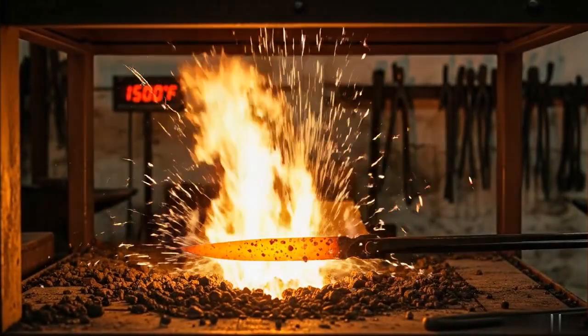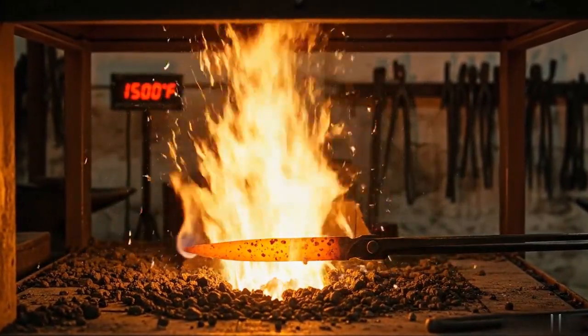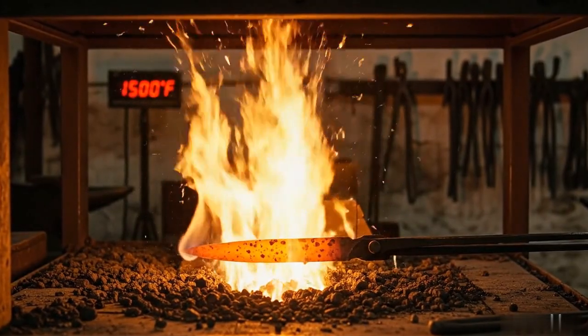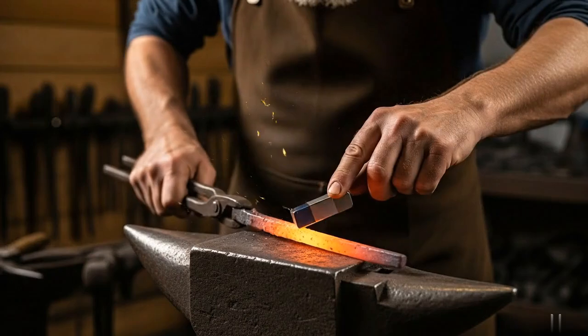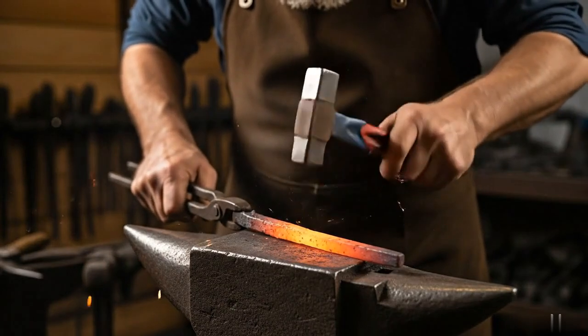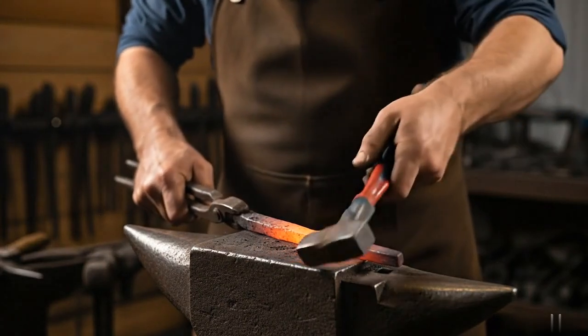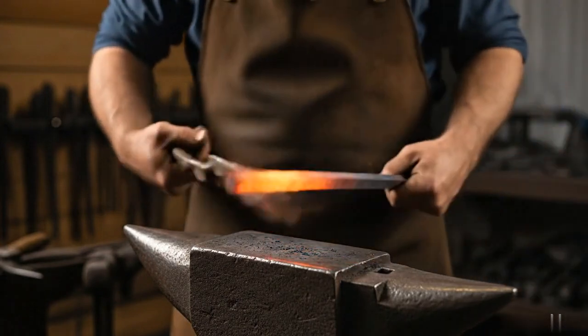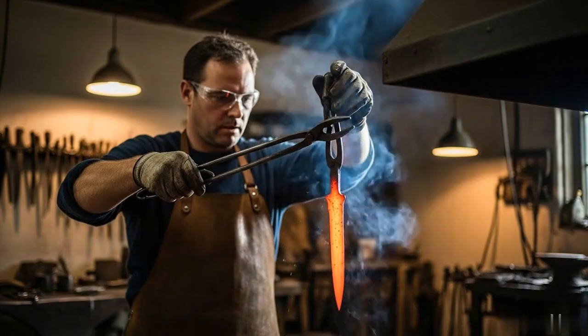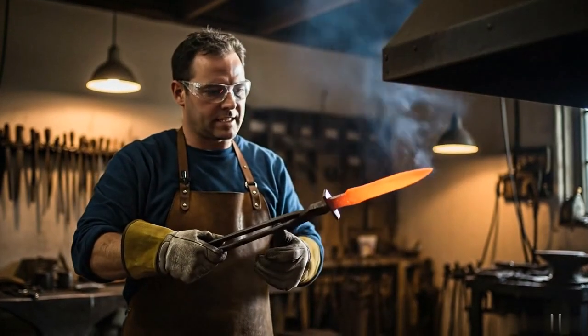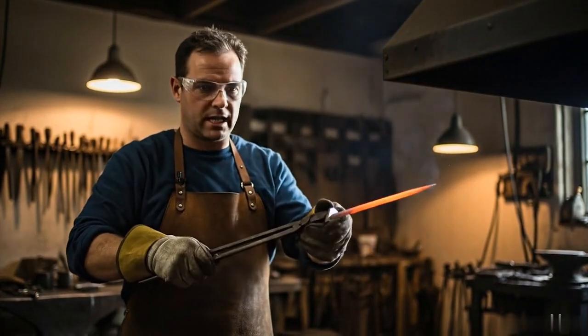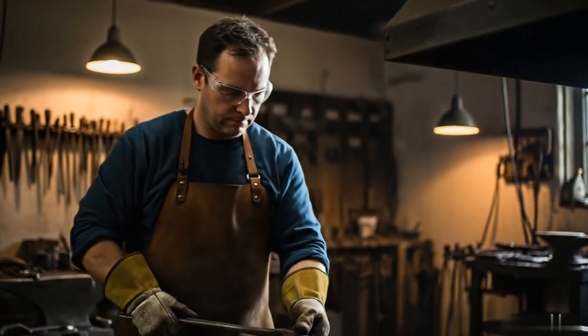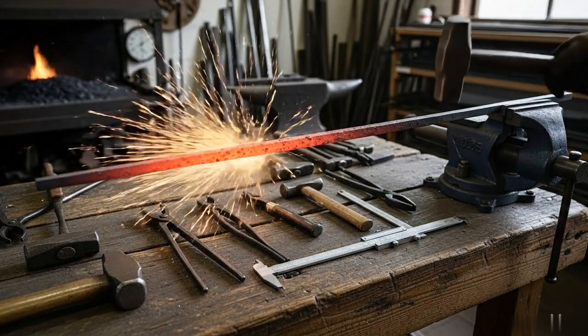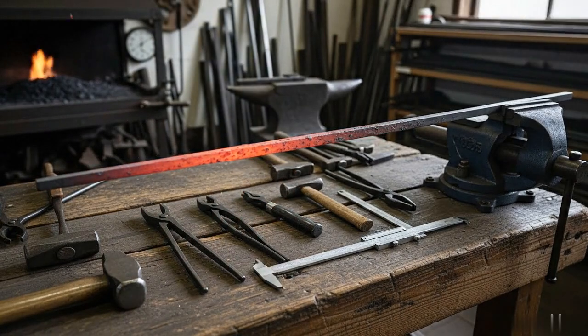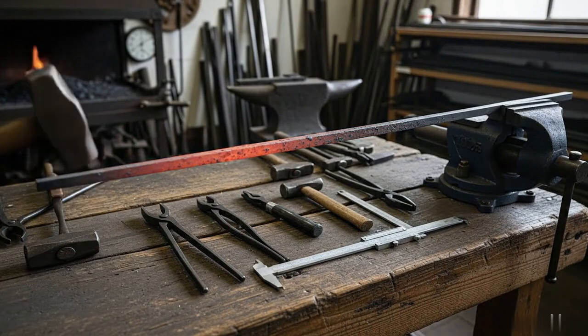I place the blade back in the forge and heat it evenly to around 1,500 degrees Fahrenheit. A simple magnet tells me when I am at critical temperature, as steel loses magnetism right there. Once it hits that temperature, I pull it out and just let it cool in still air. This lets the steel's grain structure relax and refine, preparing it for the shock that is coming.